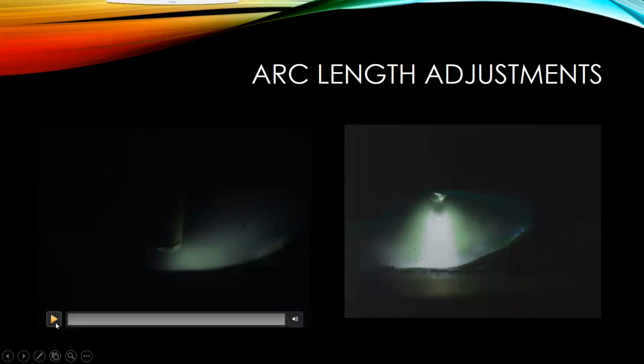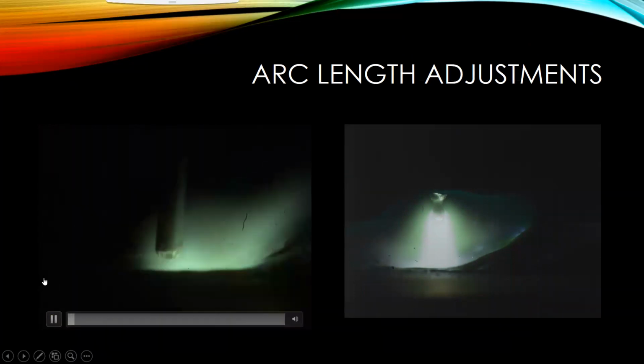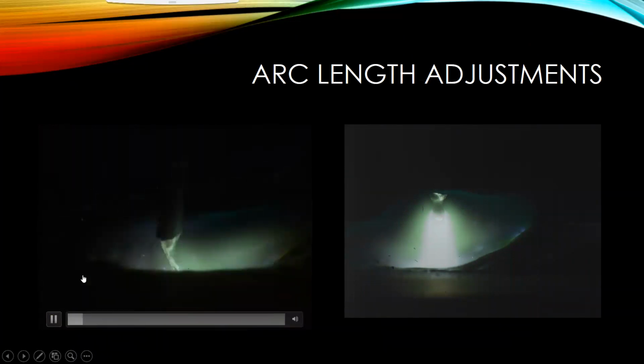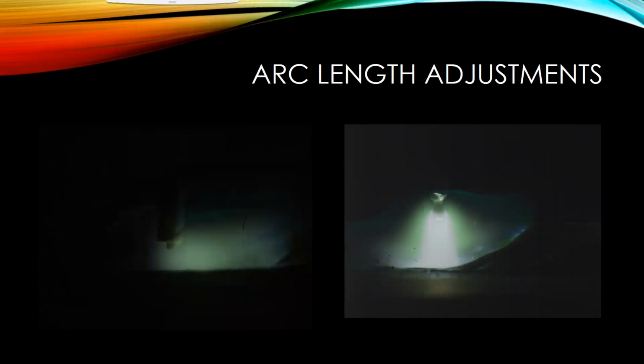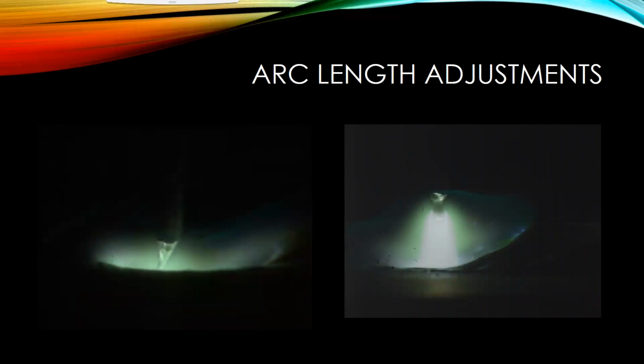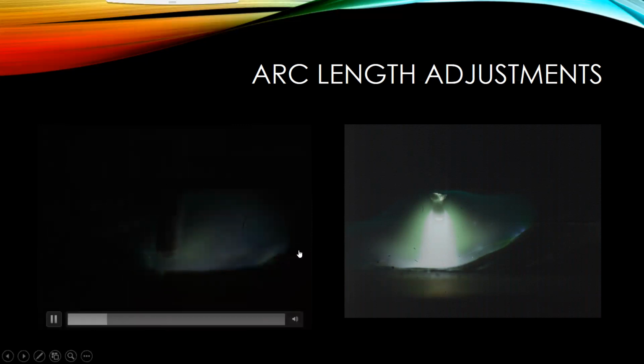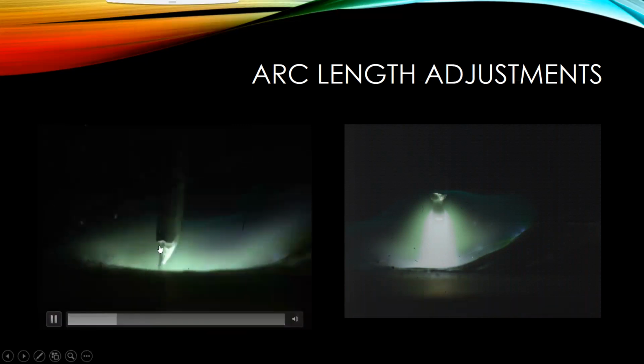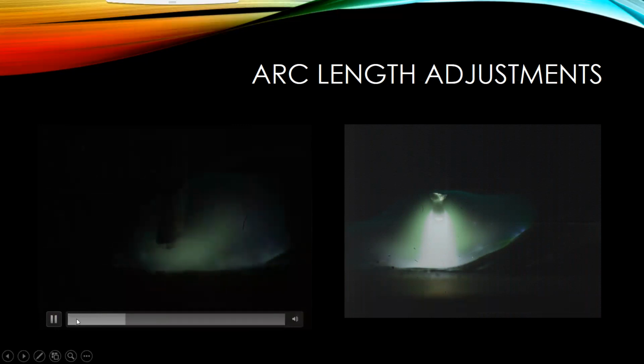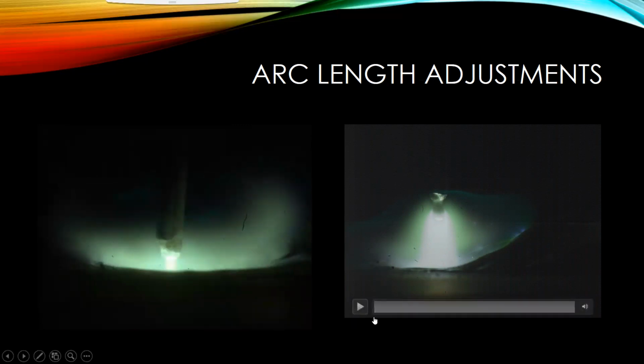Here I have some zoomed in slow motion video to see the end of the wire. So this first one, we're going to have a tighter arc length. So you can see that overall distance is not very far between the end of the wire and that puddle. And then as we increase that arc length, you can see it's going to transfer that droplet farther across the arc.